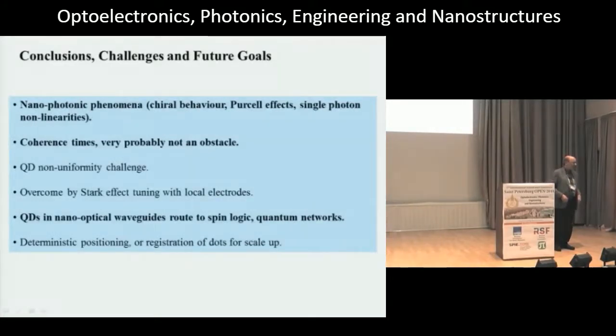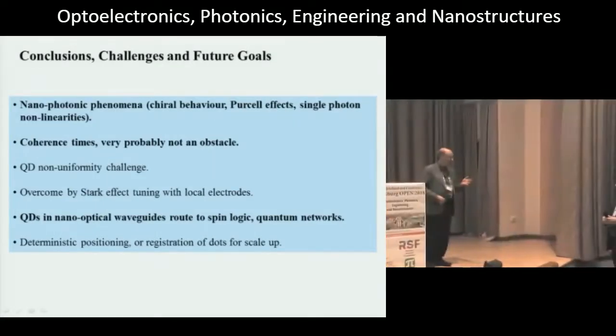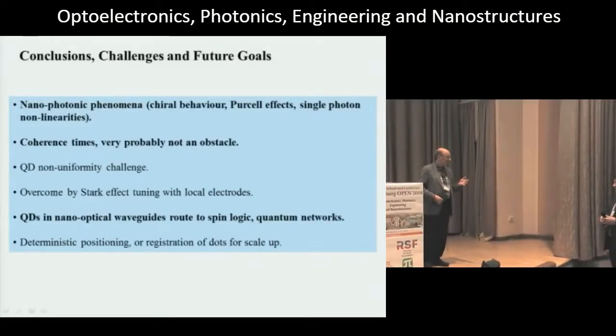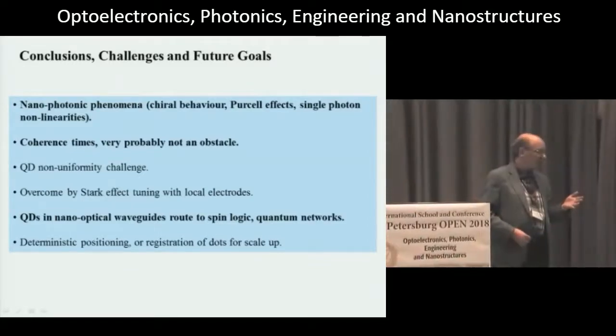So this is very likely a low temperature phenomenon, because even if you go to, say, gallium nitride systems, which are more stable at room temperature, the coupling to phonons degrades very strongly the coherence properties.